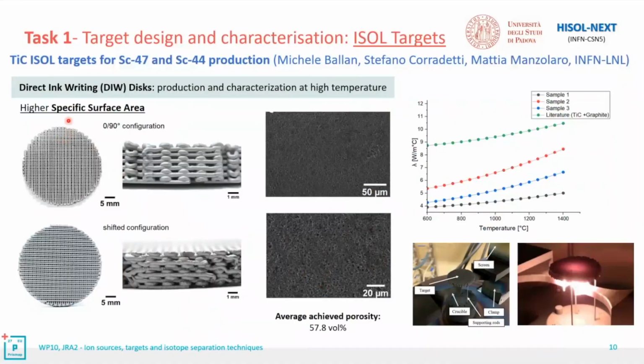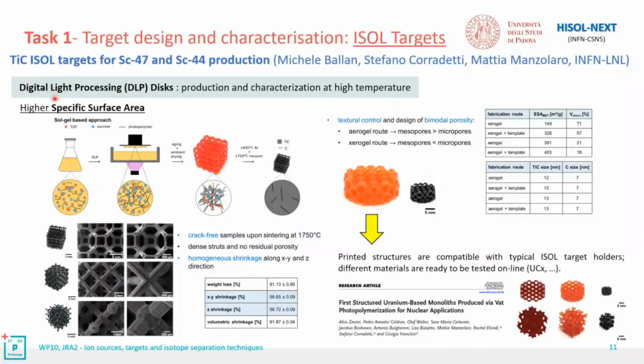And so we moved forward, describing and defining a new material with a higher specific surface area. In particular, we adopted at the beginning the direct ink writing technology, that is an additive manufacturing technology. This is the result we obtained. The material is satisfactory, but not enough, in the sense that the geometrical accuracy was not perfect, I would say. So we moved to this other technology developed in collaboration with the University of Padova and the ISOL Next initiative financed by INFN. With digital light processing, that is another additive manufacturing technology, we developed these complex structures that are characterized by an extremely high specific surface area.